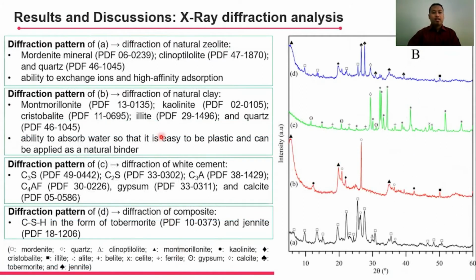And then for X-ray diffraction analysis, the diffraction pattern of A refers to the diffraction pattern of natural zeolite that contains mordenite, clinoptilolite, and quartz. The mordenite mineral has the ability to exchange ions and high affinity adsorption. The diffraction pattern of B refers to the diffraction pattern of natural clay that contains montmorillonite, kaolinite, cristobalite, illite, and quartz.